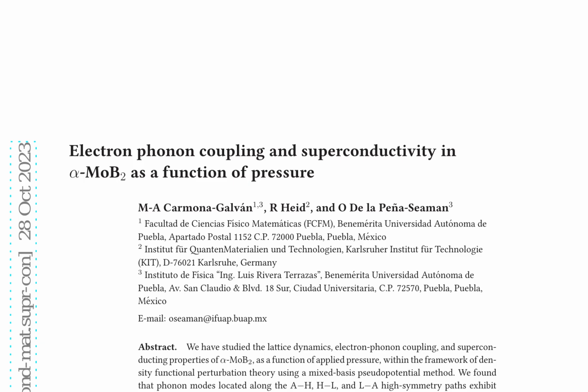Researchers employed density functional perturbation theory and a mixed basis pseudopotential method to investigate the lattice dynamics, electron-phonon coupling, and superconducting properties of alpha MoB2 under applied pressure. Analysis of phonon modes along high-symmetry paths revealed that those with large phonon line widths significantly contribute to the electron-phonon coupling constant. However, the highest frequency optical phonon modes, dominated by B vibrations, have a marginal impact on the electron-phonon coupling constant. Instead, acoustic low-frequency modes of predominantly MoB character largely controlled the electron-phonon coupling constant.